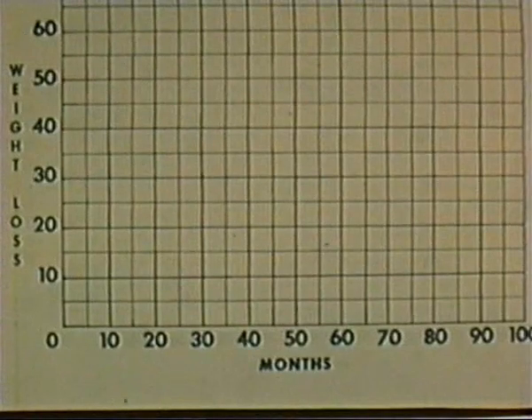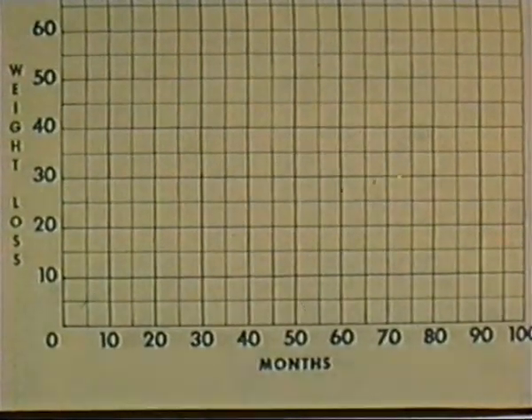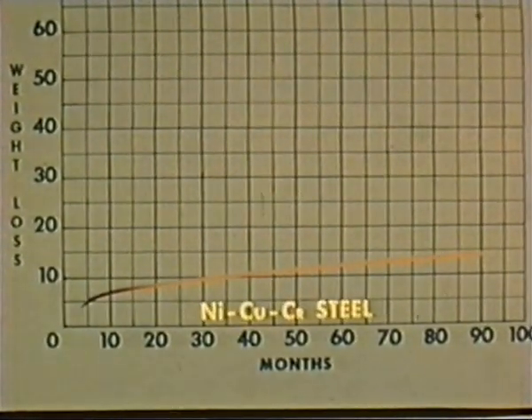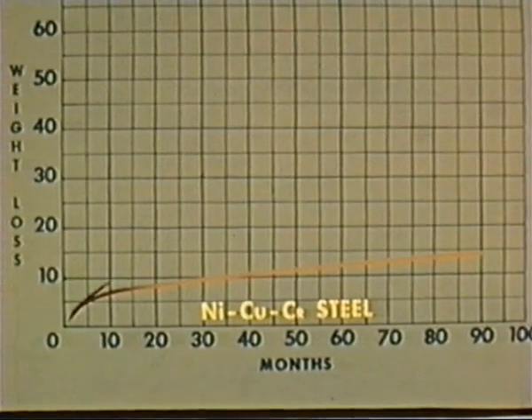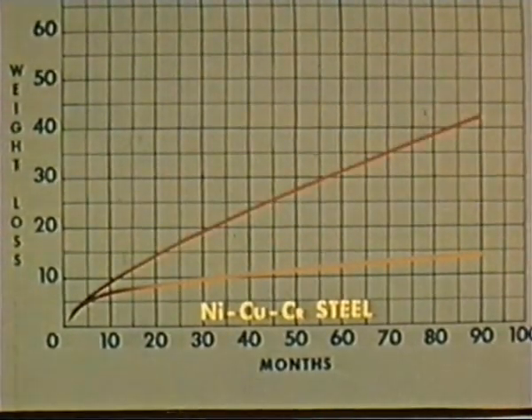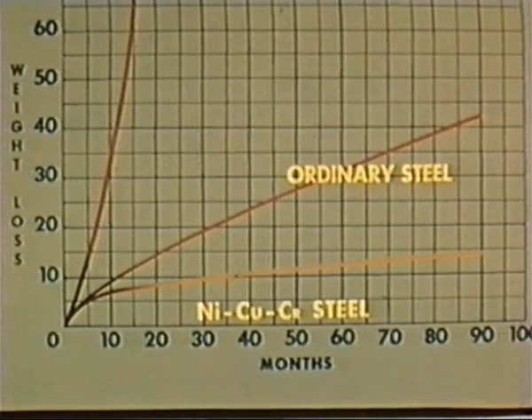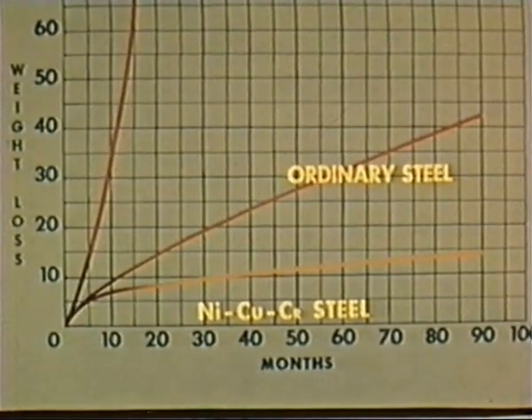As shown by the weight loss versus time curves of these 3 steels, they all corrode at about the same rate at the start. But as the more protective rust develops on the nickel-copper-chromium steel, its rate of weight loss diminishes considerably, while the rate remains practically constant on the ordinary steel and actually increases a little on the steel of low copper content.